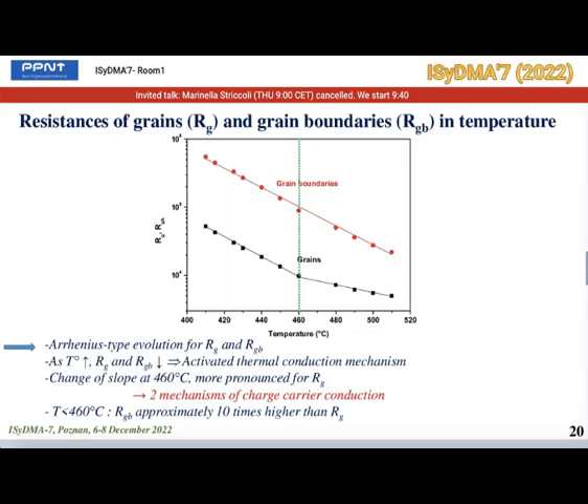Here we have plotted the resistances of grains and grain boundaries. As we can see, they decrease with the temperature increase, showing an activated thermal conduction mechanism. We can see an Arrhenius type evolution with a change of slope at 460 degrees, more pronounced for the grains resistance, which indicates that there are two mechanisms of charge carrier conduction.